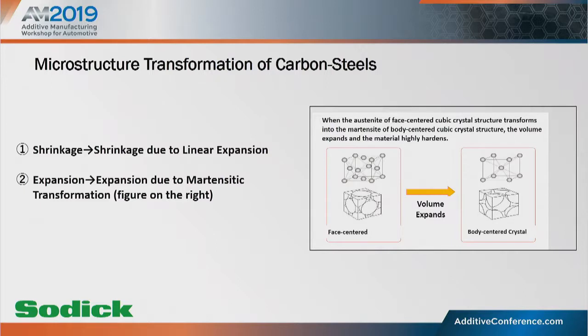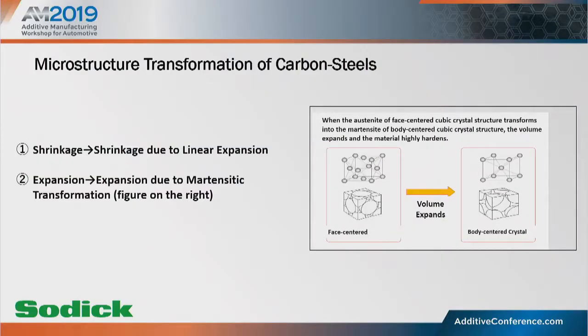But in part, these transformations are actually predictable based on some of the chemical composition of those parts themselves, particularly of carbon, which has a very predictable change in the crystal structure, which will determine just how much it expands during the cooling process. Which means if you can balance that expansion with the anticipated shrinkage due to heat, you can actually achieve a much more stable part and have a much more reliable tolerance across that entire part.